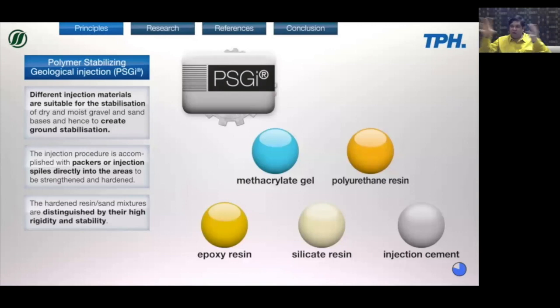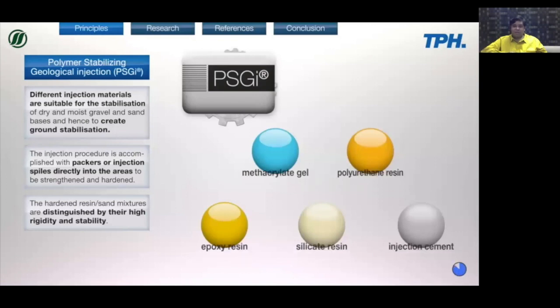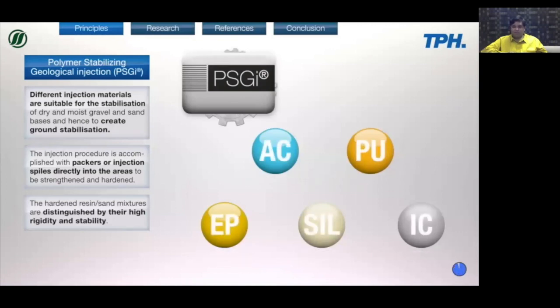So if you have large cavities in your ground, for example a cavity of maybe 70 or 80 liters, you can just pump in about 1 or 2 liters of this resin into that place. And it almost swells up. We'll also see this in one of the case studies. And of course, the last but not least is the cement-based material for injections.